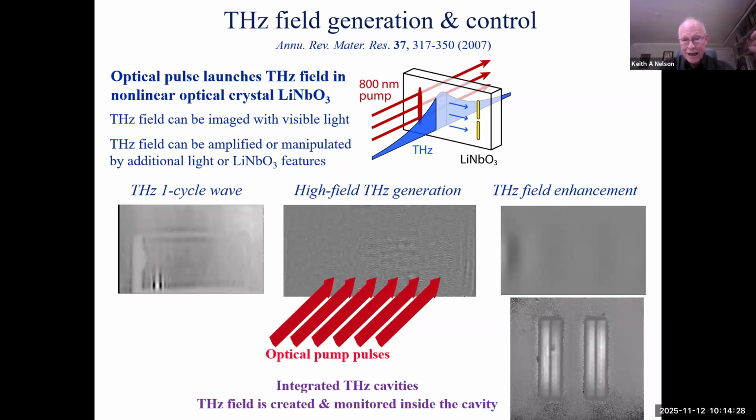What is really happening is the optical field is driving strongly polar lattice vibrations. It's rocking that niobium +5 ion through stimulated Raman scattering, inducing oscillations of that ion, surrounded by a cage of oxygen anions that has a very strong dipole, so it radiates. It couples strongly to terahertz frequency light. And so what we generate, strictly speaking, are terahertz phonon polaritons.